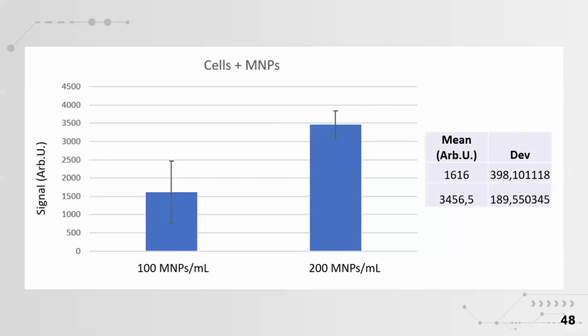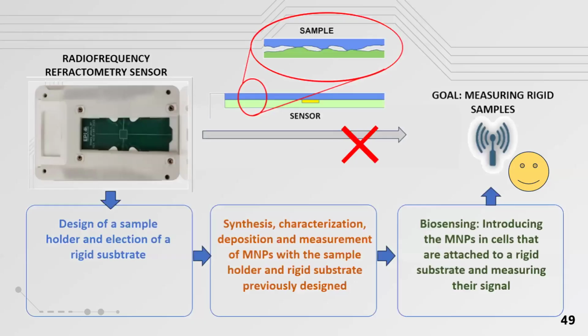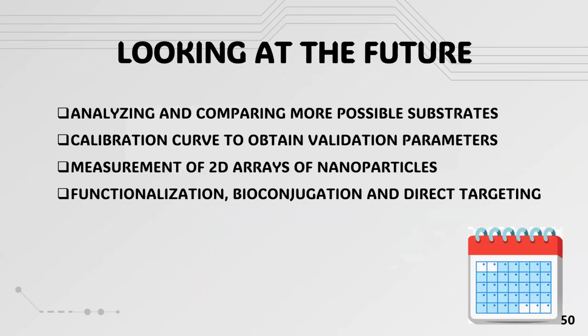As you can see, we obtained twice the signal from the cells that had double the magnetic nanoparticles, which is what we expected. So we can conclude with this that we have achieved the goal of measuring on rigid substrates with our sensor. As plans for the future, we would like to analyze and compare more possible substrates that can work with this new system so that we can make better calibration curves to obtain validation parameters, such as the detection limit or the quantification limit.